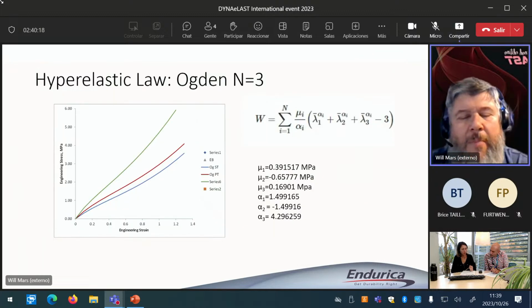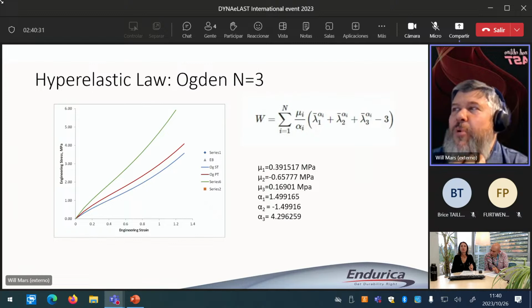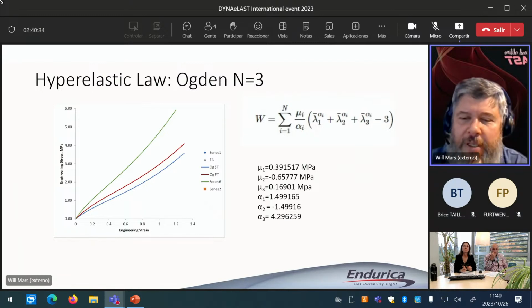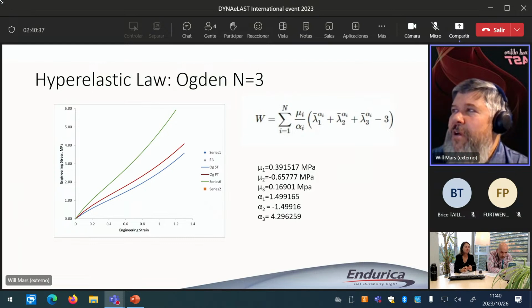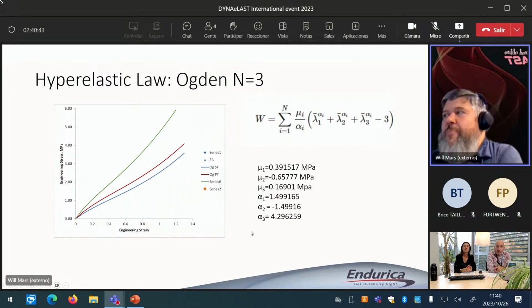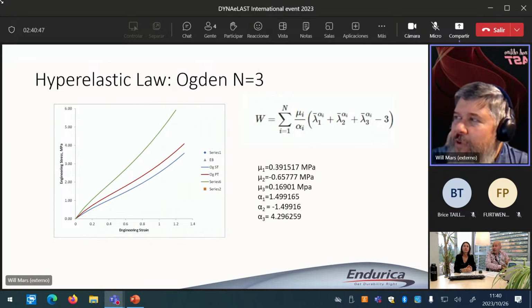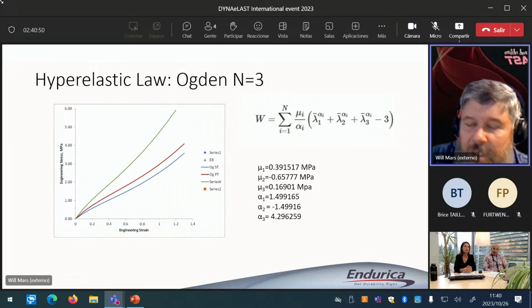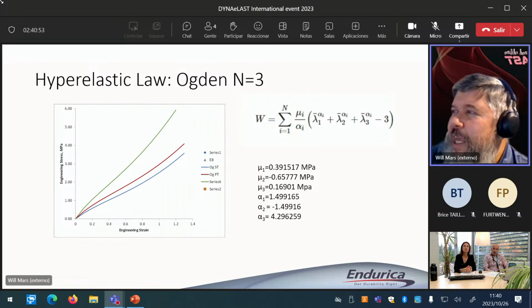I mentioned that we are modeling the nonlinear elastic behavior of the rubber. To do that, we're using a third order Ogden hyperelastic law. What you're looking at here are curves showing the simple, planar and equibiaxial tension stress strain curves for that material, along with the strain energy density function definition, W, and along with the material parameters mu1, mu2, mu3, and alpha1, alpha2, alpha3. I would say this is a pretty standard approach to modeling these types of materials. By the way, it's a natural rubber. I should mention, a filled natural rubber.